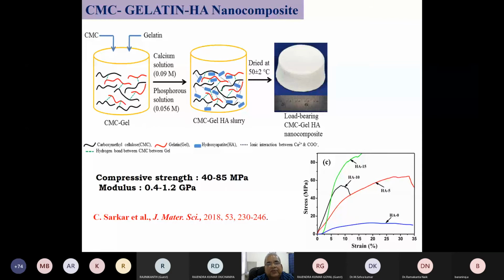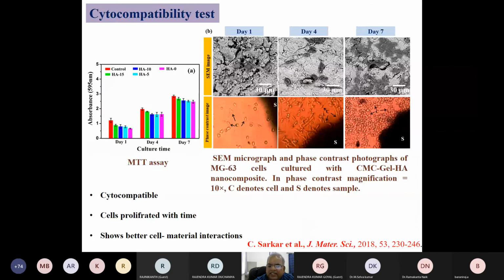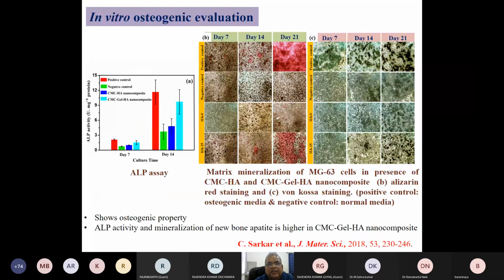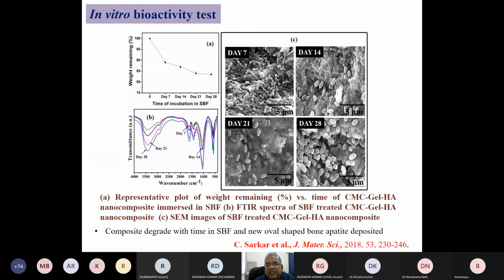Then further, to increase the mechanical strength, one of our PhD students made a composite of the polymer before nucleating the hydroxyapatite. She took CMC and gelatin, the two polymers together, and then synthesized the hydroxyapatite in situ into the 3D structure. She dried it at 50 degrees centigrade for rapid drying, and here we got a compressive strength of the order of 85 MPa, and the modulus was 1.2 GPa. So we were increasing the modulus. Then she carried out the cytocompatibility test and so on, and confirmed that they are bioactive, osteoinductive materials which can instruct the body to start healing itself.